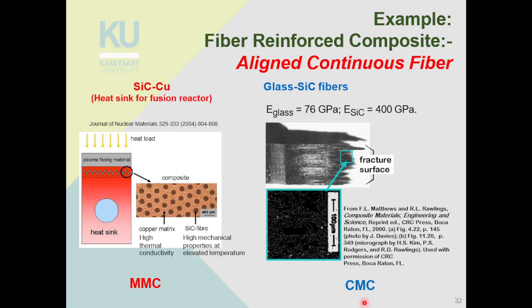And if you look more closely, you can see some sort of boundaries in the copper matrix as well. Because the way they produce this, they are coating silicon carbide fibers with copper, and then they are stacking those copper coated silicon carbide fibers together, and then they press them together, and then they heat them to make a big chunk, right? So they start off with silicon carbide fiber and coat that fiber with copper, you do that to a lot of silicon carbide fiber, and then you stack them together, and then you heat them up, you get this bulk of silicon carbide reinforced copper heatsink.